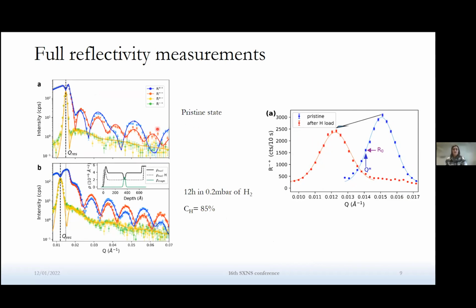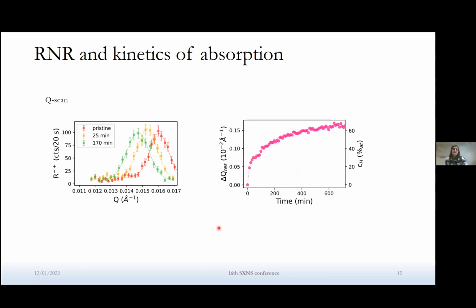However, each of these curves took hours, while in reality, the kinetics of absorption is pretty fast, in the order of a few minutes. So in order to see that kinetics of absorption, I employed RNR, resonant neutron reflectometry. And we have done so with two modes. The first mode is a Q-scan, where we just follow our resonance with time. So we just scan a very small Q range, and this allows us to decrease the measurement time. And knowing the shift, we can retrieve the hydrogen content, as you can see here.